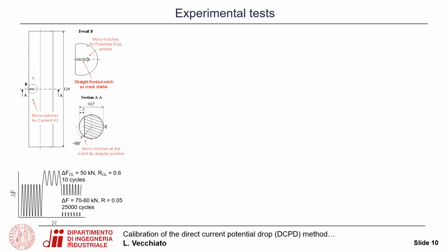The experimental tests were performed adopting cylindrical specimens with a straight front at the crack starter notch. The specimens were tested with constant amplitude loads and with overloads, 10 cycles of overloads every 25,000 cycles of constant amplitude. The overloads were applied at a smaller load range, stress range, but a higher load ratio.